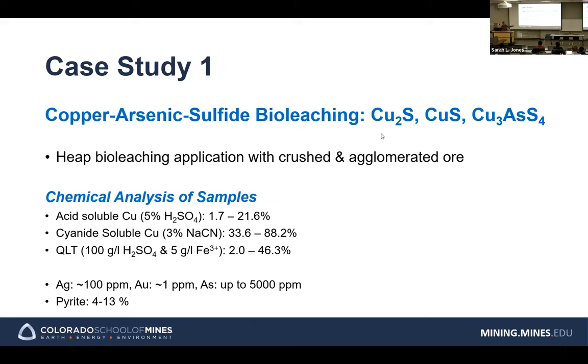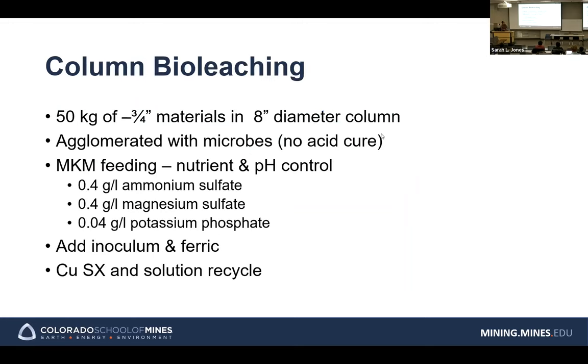And arsenic, as you can expect, because we have an arsenic containing copper sulfide, arsenic concentration is high. And we ran the column test. The column test is a simulation of heap leaching. So heap leaching is, we mine it, we crush to 1.5 inches or 3/4 inches, or sometimes close to 1/2 inches, and then use an agglomerating drum, and place it on the leach pad, and sprinkle leach solution, and then we can get the copper out. So that's heap leaching.